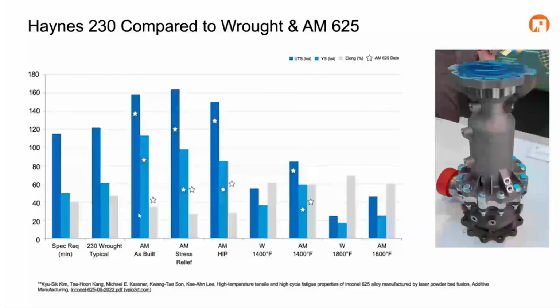But when we go to the as-built, or additive manufactured version, we can see the AM as-built, AM stress relieved, and AM hipped. Across the board, we're able to still retain most of our ductility while getting much higher yield strengths as well as ultimate tensile strength.